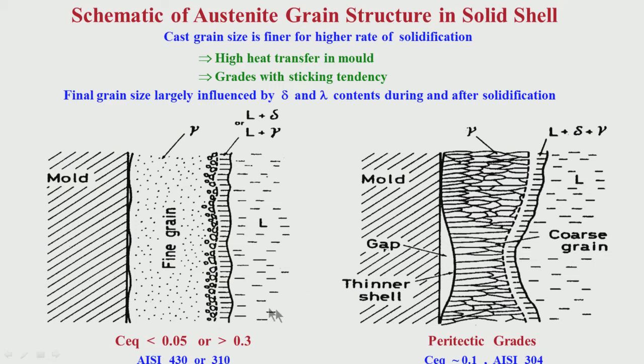So, when we have a sticking tendency, what do we have? We have fine grains. Solidification is either through liquid plus delta or through liquid plus gamma. That means either very low carbon equivalent or very high carbon equivalent, either ferritic 430 or austenitic 310. So, these are the chemistries where you have this type of structure because of sticking characteristics. And in the so called peritectic grades, where we have carbon equivalent of say 0.1 or AISI 304 stainless steel, what is happening here?